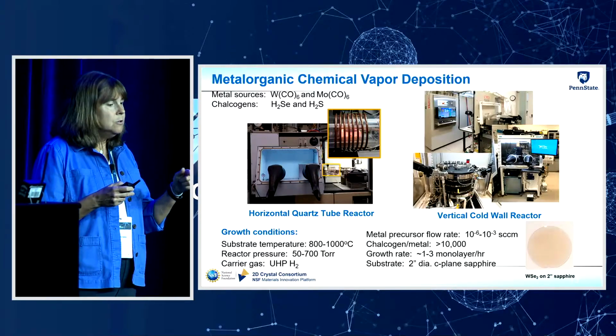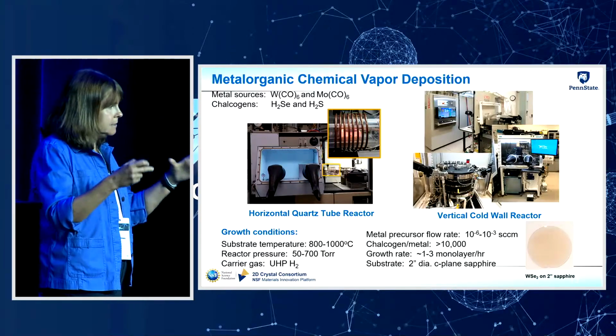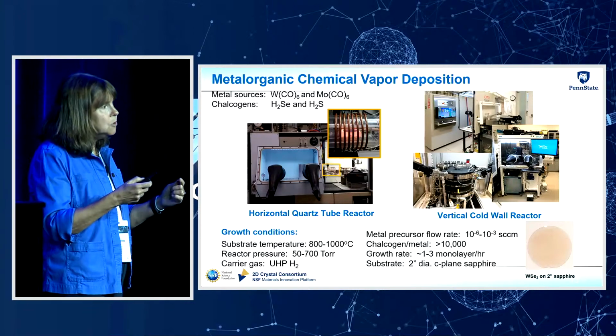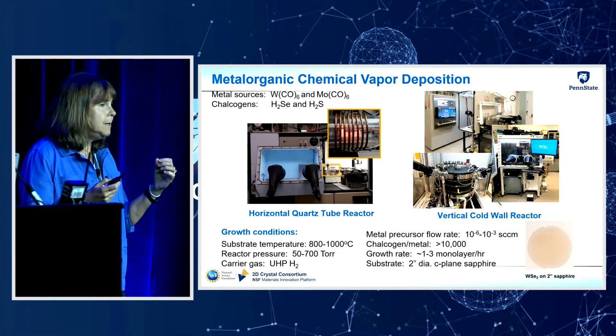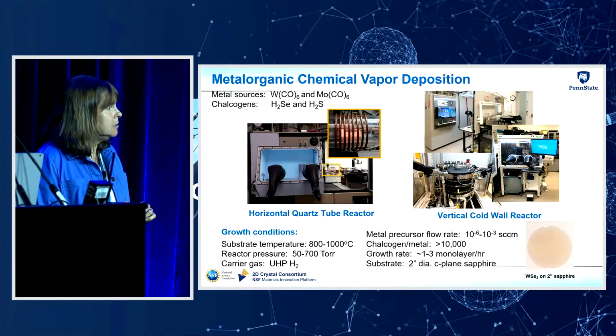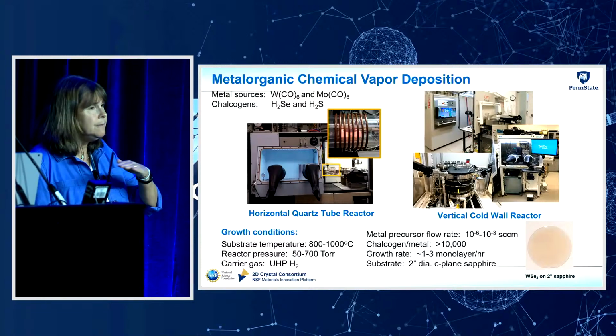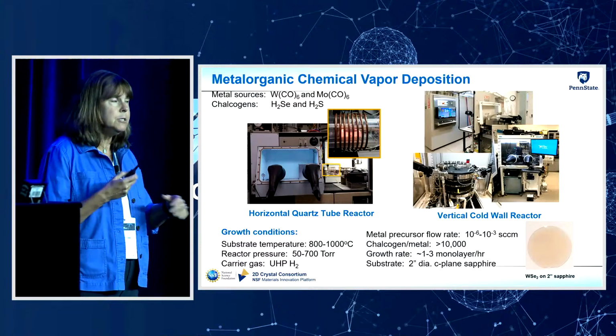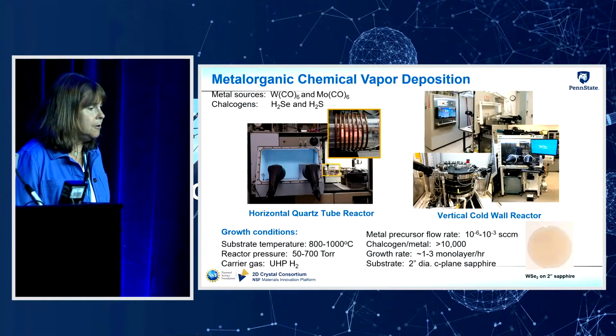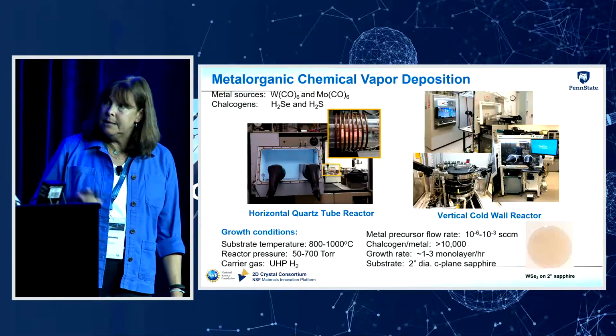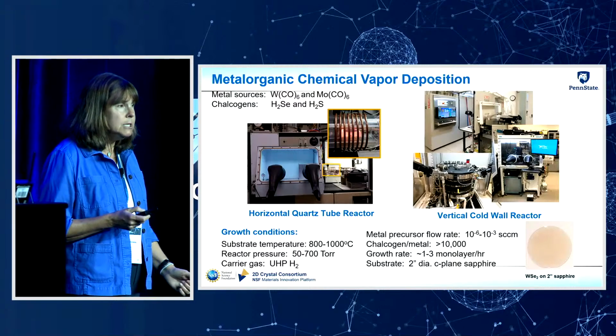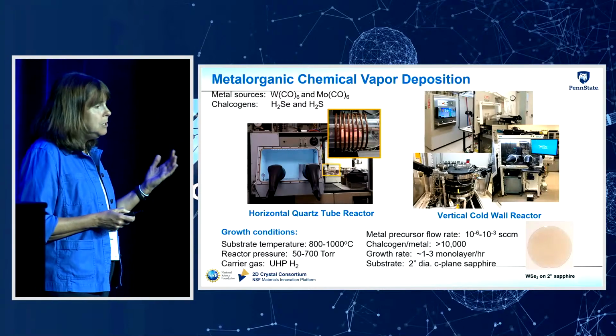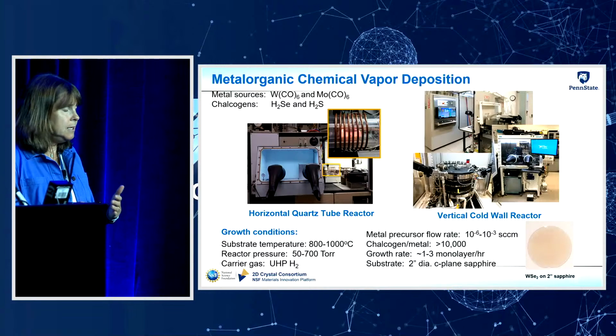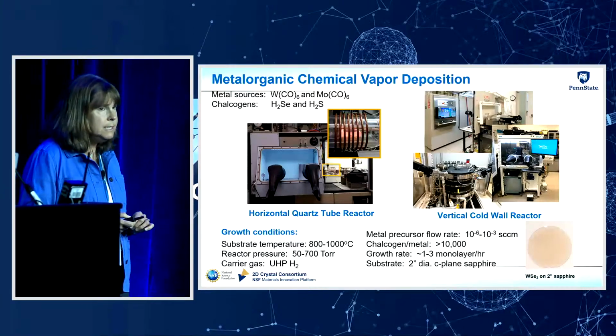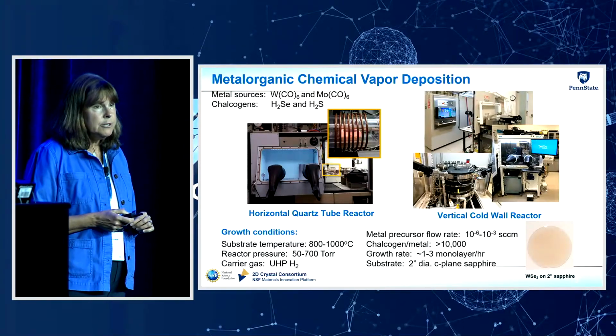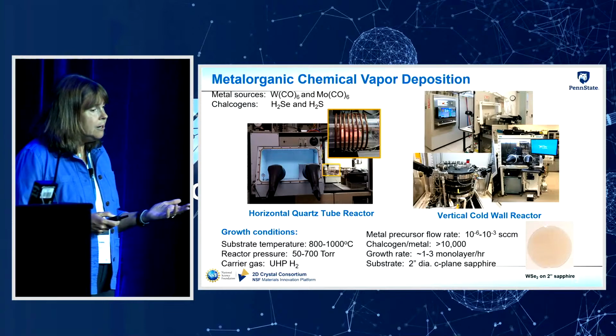The vertical cold wall reactor that I'm showing has a stainless steel chamber, and we have optical ports where we have an in situ spectroscopic ellipsometer, and that enables us to monitor the coverage of the surface as a function of time. So it gives us some way to monitor our growth process. And at the bottom, this is just a snapshot of the conditions that we use. So as I mentioned, we use high substrate temperatures in the range of 800 to 1,000 degrees C, moderate reactor pressures. We use hydrogen as the carrier gas.